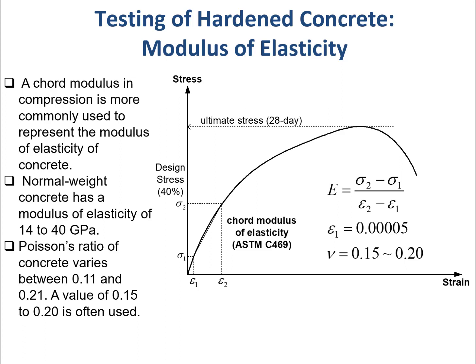This process is standardized by ASTM C469. Basically, we need to find 2 points on this nonlinear stress strain curve. The first point, epsilon 1, sigma 1, is found by first finding epsilon 1. Epsilon 1 should be approximately equal to 0.00005, and sigma 1 is the stress corresponding to this strain level. And the second point is located by finding sigma 2.